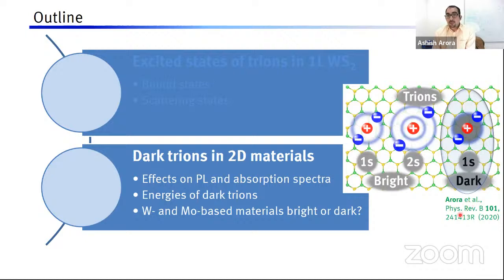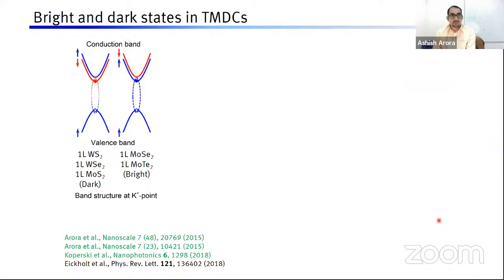So we are going to discuss dark trions now, which do not interact with light. Let us take a look at the band structure of tungsten disulfide or tungsten diselenide or molybdenum disulfide first. And in this case, what has been realized or agreed upon by the community at the moment is that the conduction band is split due to spin orbit splitting, and the bottom of the conduction band has an opposite spin than the top of the valence band.